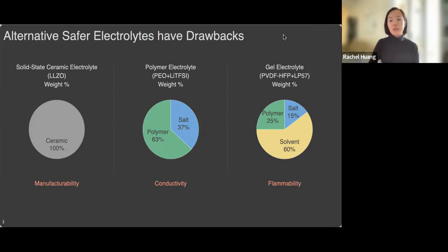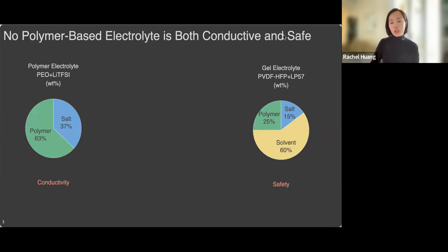Moving on to the more manufacturable electrolytes, we have polymer-based electrolytes. Polymer electrolytes lack ion conductivity, and gel electrolytes are still flammable. I'll go deeper into these 2 types of electrolytes. Polymer electrolytes replace the flammable solvent molecules in normal electrolytes with polymer. Normal electrolytes have small molecules that move quite fast, while polymers move quite slow, and as a result the ion conductivity of the polymer electrolyte is quite low. That makes those electrolytes have to be run at elevated temperatures, like 60 to 80 Celsius.